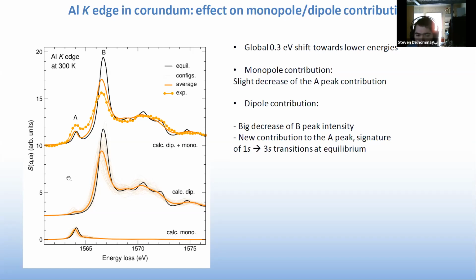We know that the A peak here is supposed to be a signature of 1s to 3s transitions. And so we're not supposed to see this peak. So we are going to try to somehow explain it. And the projected density of states calculation can help us do just that.